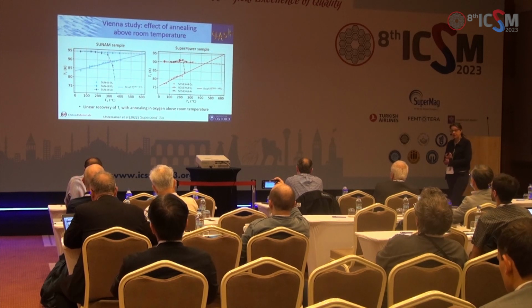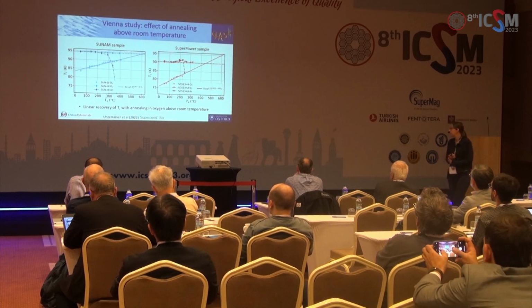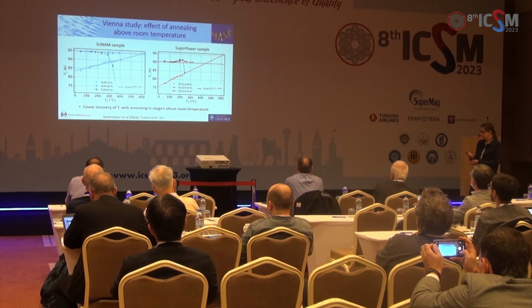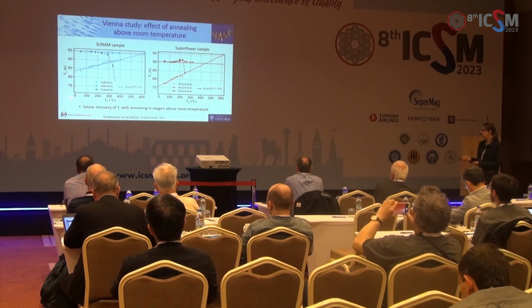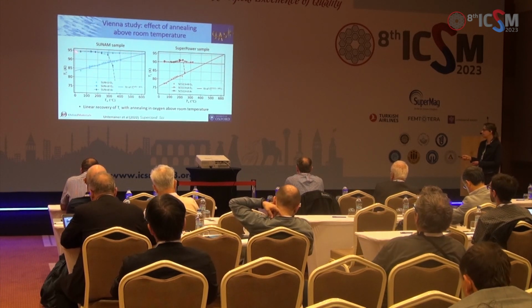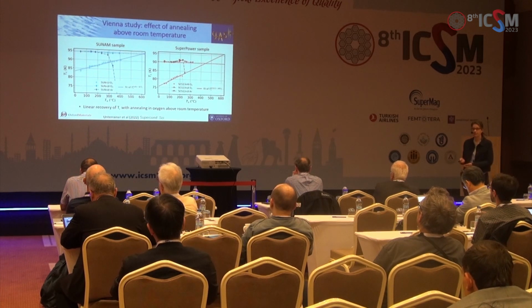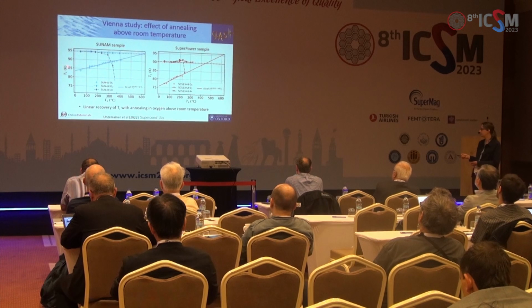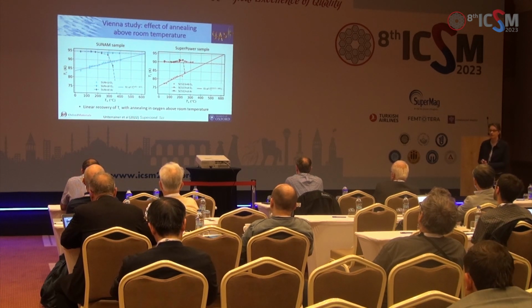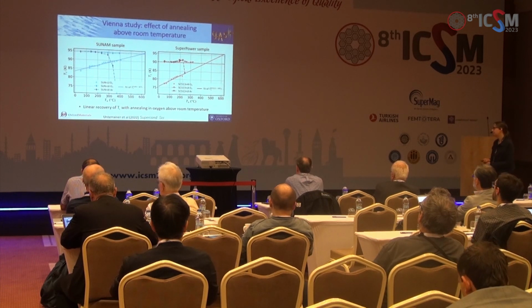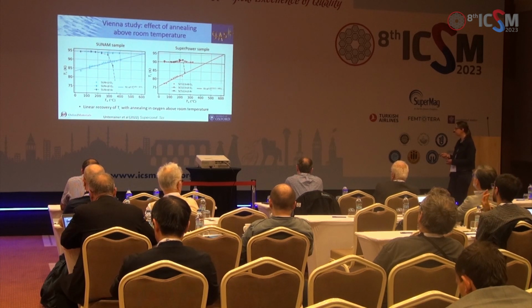So there's been other studies on annealing. These are recent studies by the Vienna group on two different samples here, one SUNAM, one superpower. What you're looking at here is TC as a function of annealing temperature. So you can see if you've got unirradiated samples, you're not doing any damage by doing this annealing. It's being done in oxygen, so we're not pulling oxygen out. However, if you've got the degraded irradiated sample and then we anneal, we can see we're getting TC going back up. That's very similar to the kind of recovery that we were seeing in the cold irradiated samples.